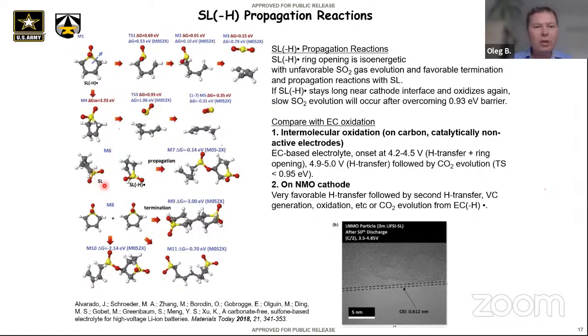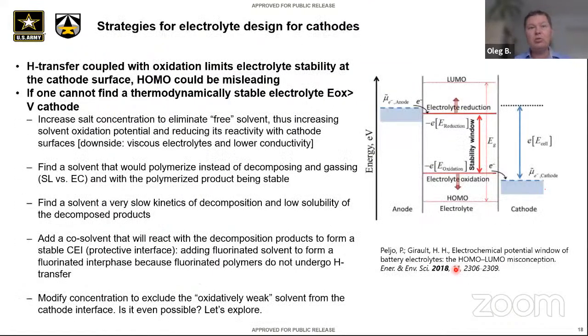Instead, it would prefer for sulfolane to react with another sulfolane and have a propagation reaction or condensation reaction. And that will form an SEI. If you abstract a proton, again, it will favor the propagation reaction. So that gets us a second mechanism. Hey, look, we just need to find a solvent which doesn't evolve gas like CO2 upon opening up. If it prefers propagation reactions, then you can form such a nice CEI film as has been observed on this high voltage nickel metal oxide particle. So that gets me to the conclusion for the first part, which says that H transfer is very coupled with the majority of oxidation for hydrogen-containing electrolytes, unless there are double bonds like in VC.